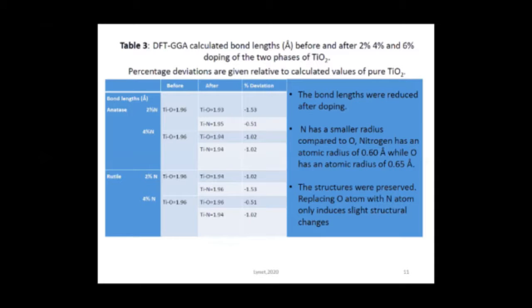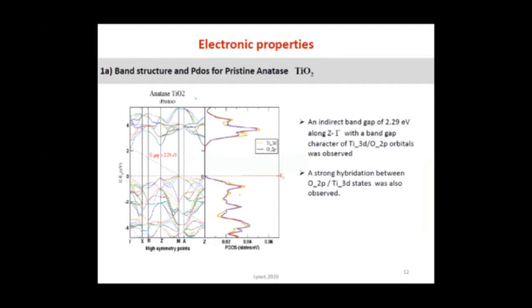Then we went ahead and studied the electronic properties. For the pristine materials, pristine anatase, we have the band structure. We were studying the electronic properties by focusing on the impact of the dopant on the band gap, because we have stated earlier that we need to reduce the band gap of TiO2 so that it can absorb a major part of the spectrum. So we got an indirect band gap of 2.29 eV between Z and gamma, we can see that. And from PDOS, we can see that the band gap character is oxygen 2p and titanium 3d. So there's some strong hybridization between the two.